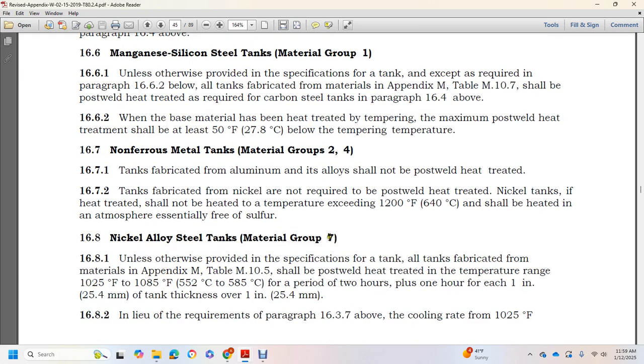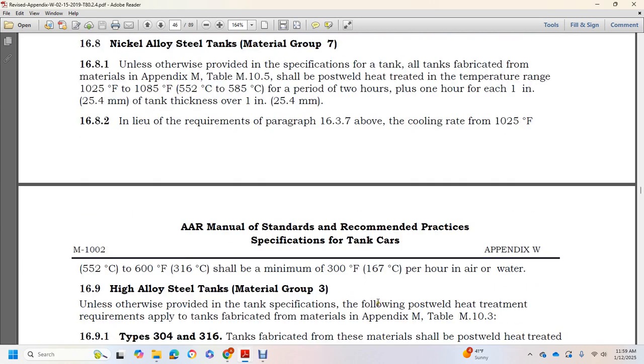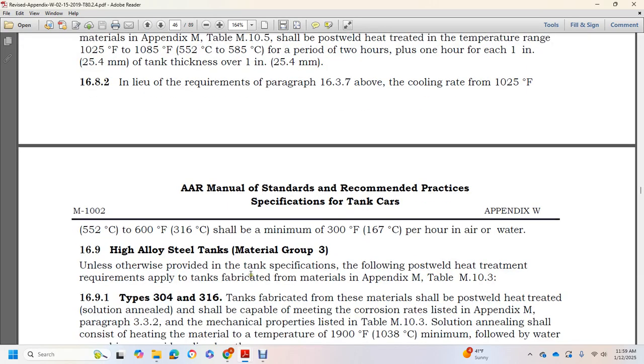Nickel alloy steel tanks, material group 7. Unless otherwise provided in the specification, all tanks fabricated from the materials in Appendix M, Table M10-5, shall be post-weld heat treated at a temperature range of 1025 to 1085 degrees Fahrenheit for a period of 2 hours, plus 1 hour for each inch of tank thickness over 1 inch, in lieu of the requirements of paragraph 16.3.7 above. The cooling rate from 1025 to 600 degrees Fahrenheit should be a minimum of 300 degrees Fahrenheit per hour in air or water.